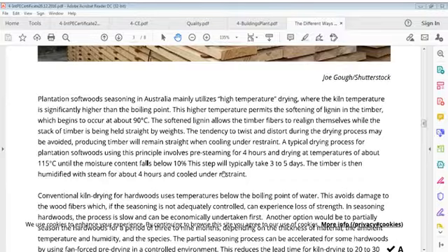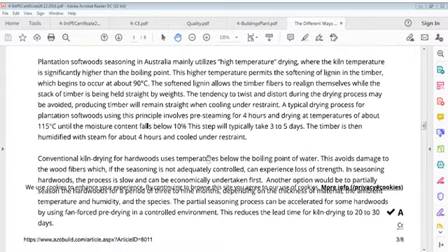Plantation softwoods using this principle involves pre-steaming for 4 hours and drying at a temperature of about 115 degrees Celsius until moisture content falls below 10%. This step will typically take 3 to 5 days. Timber is then humidified with steam for about 4 hours and cooled under restraint.